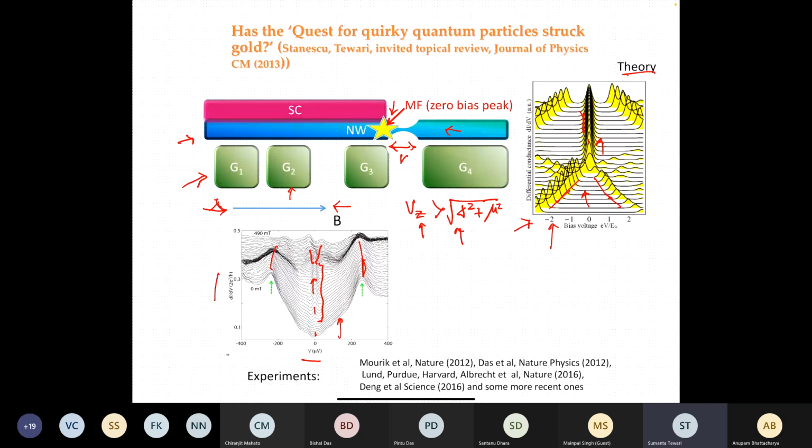that if you have a Majorana fermion, those of you who know tunneling conductance experiments in superconductors know that if you have an Andreev bound state at the interface between the metallic tip and your superconductor, typically the peak height, if it's an Andreev state at zero energy, not a Majorana state, would be 4e²/h. The prediction is that if it's a Majorana state, the peak height would be 2e²/h. So that's very important. 2e²/h should be the peak height if it's a Majorana state over here.